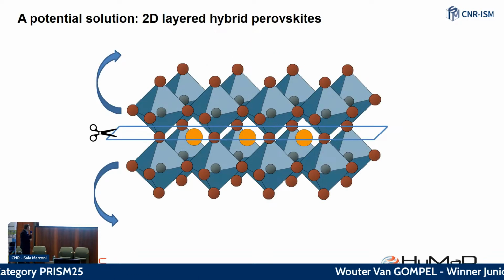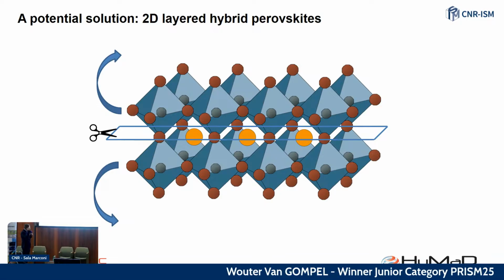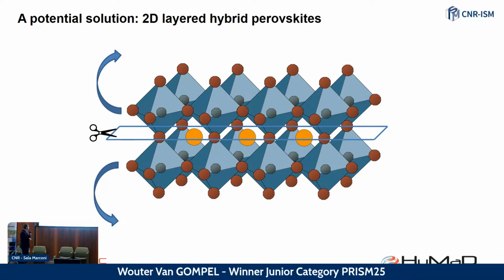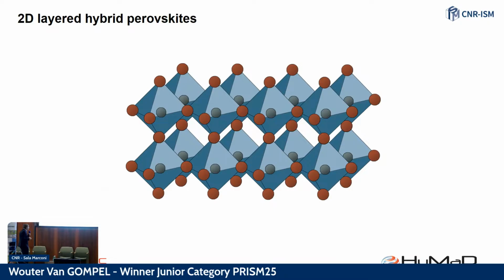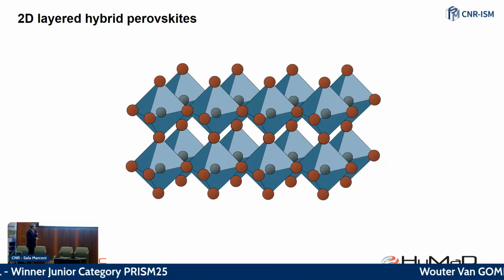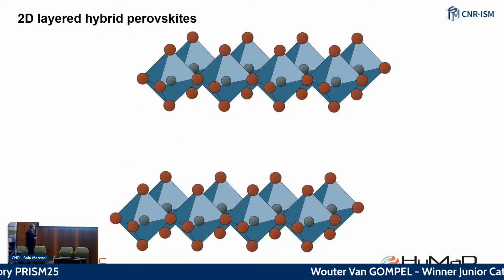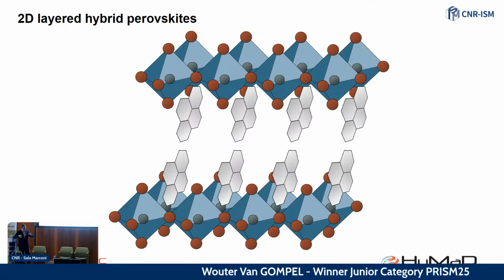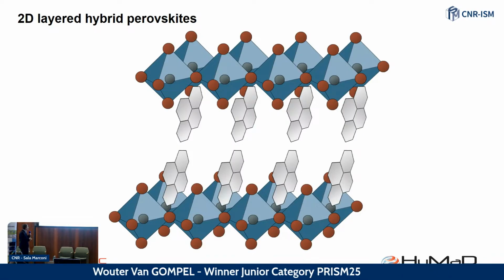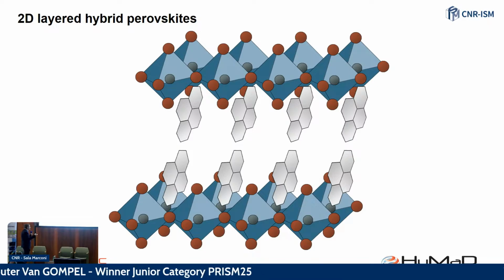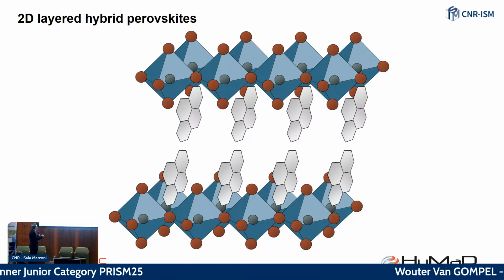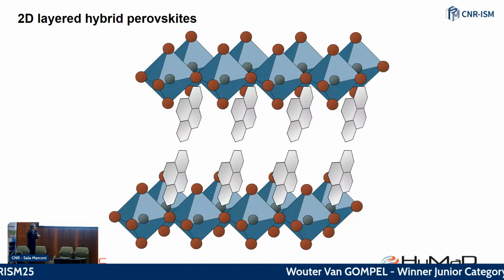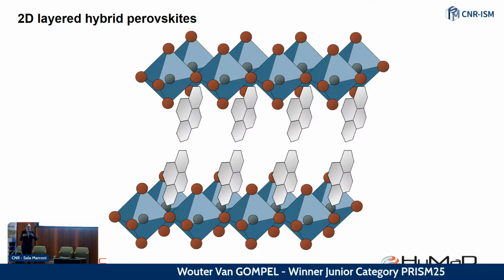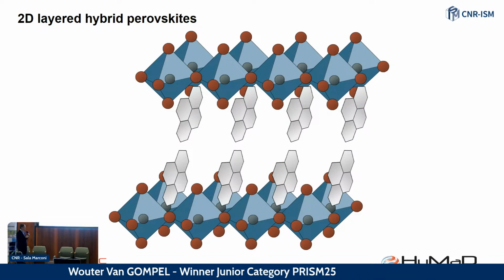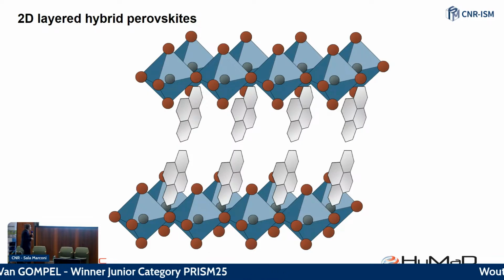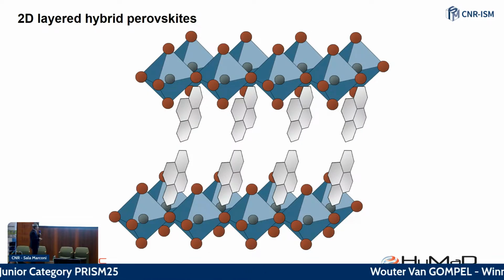And one of the potential solutions is reducing the dimensionality from 3D to 2D. So conceptually, what you do is you remove these small cations, and you open up the structure and you insert bulkier organic cations. Of course, it is purely a conceptual picture. With the bulky cations, the 3D structure cannot form anymore, and the layers are forced apart. And then you get a 2D inorganic framework. But the bulk of the material is still a bulk material, so we are not looking at morphologically 2D materials. They are structurally 2D, let's say.